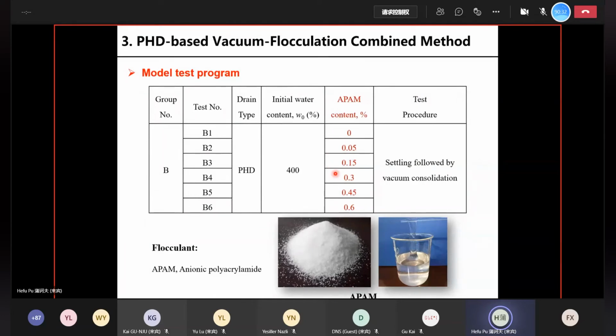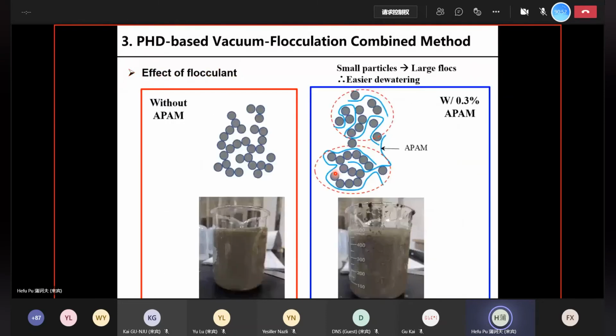The APAM is short for anionic polyacrylamide, which is a common type of flocculant that has been commonly used for water treatment. And in recent years, people have also begun to use this for mud treatment because this APAM is a polymer material. They have very long chains, and these long chains have bridging effects that can bring all the small particles together and to form large flocs.